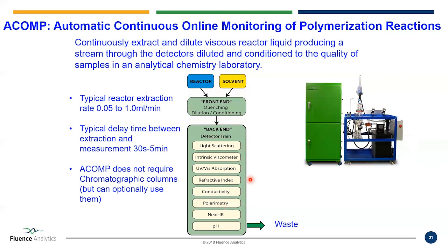Now, it's not a chromatographic technique. There's no columns here. Okay, so it's unfractionated, so you don't have all the stability problems and other headaches of GPC. Don't get me wrong, we like GPC, but we don't like to put it in factories at this time. This is a much more robust phase. You don't have wandering baselines. You have a continuous feed of this analytical grade solution.